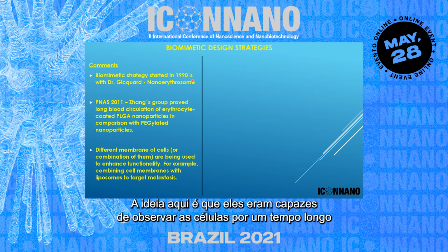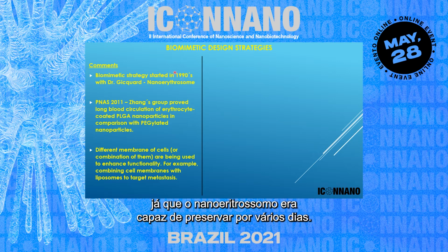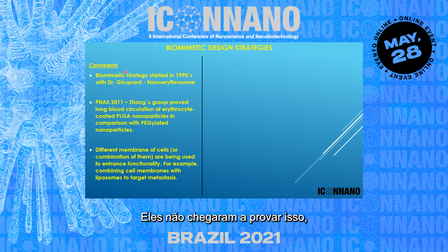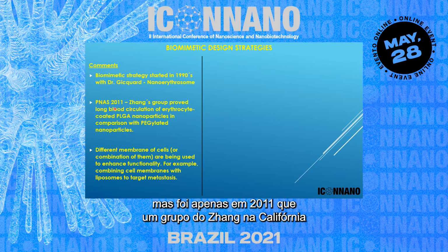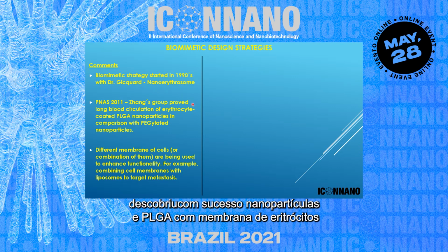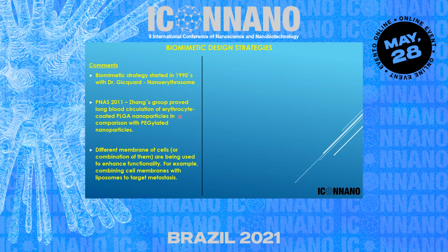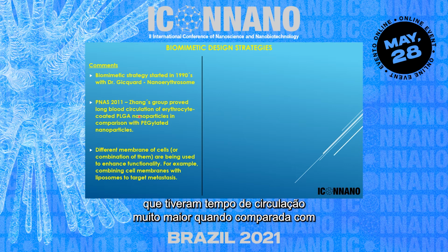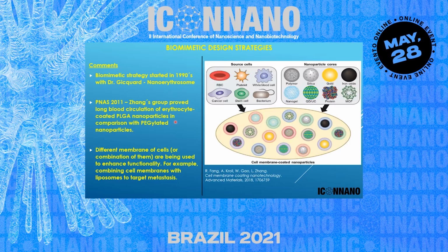The idea here was that they could observe a very long blood circulation time, since erythrocytes stay in the blood for around 100 days. Well, they had not proved this, but it was only in 2011 that a group in California, led by Dr. Zhang, proved that they had successfully coated PLGA nanoparticles with a red blood cell membrane, and that this even has a longer blood circulation time in comparison to pegylated nanoparticles.